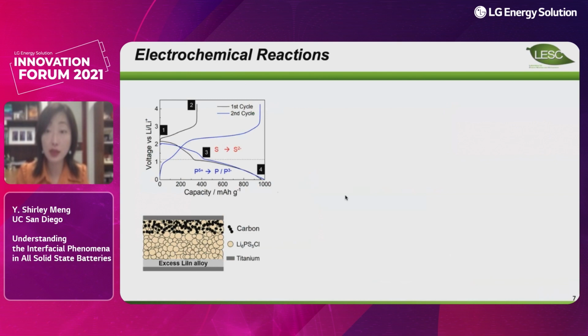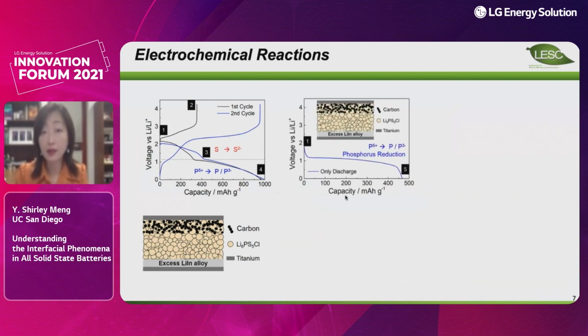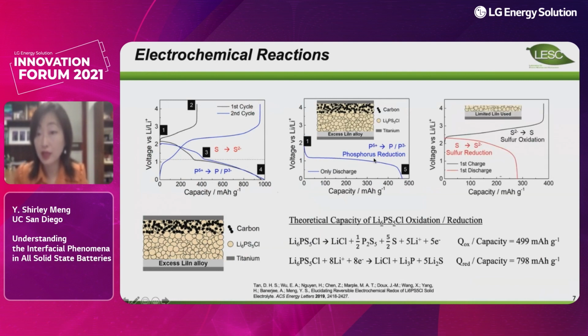So we carried out a very detailed characterization to understand the reaction mechanism of the argyrodite solid electrolyte, and both of these plateaus are carefully studied. These are electrochemical signals coming from the argyrodite electrolyte. You can see the low voltage phosphorus reduction is actually a one-step process. However, when you have sulfur, the higher voltage plateau is actually a sulfur reduction and oxidation, and it's completely reversible. Understanding this is very important because just like the liquid-based electrolyte, we need to understand the interface in order to optimize the cell cutoff voltage, the cell constructions, etc.